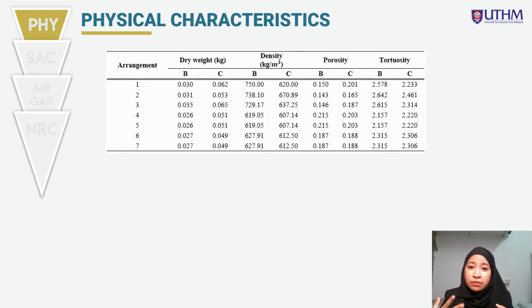If we compare samples B and C with the same arrangement, the samples made up of a bigger stalk diameter demonstrate higher density than the samples made up of a smaller stalk diameter. The samples made up of a smaller stalk diameter arranged in axial configuration showed a significantly higher porosity than the samples made up of a bigger stalk diameter. When density increases, the porosity decreases. The amount of Lepironia articulata and its diameter size will indirectly influence the porosity and other physical characteristics of the acoustic absorber. Lastly, the tortuosity is inversely proportional to the porosity.